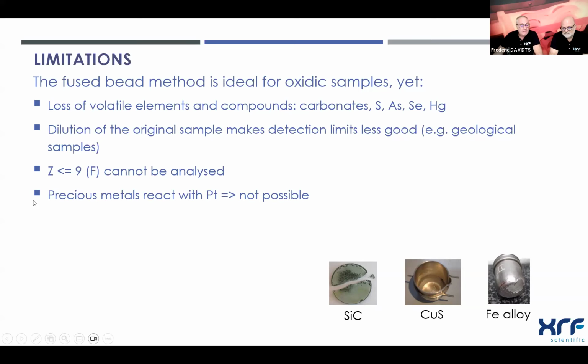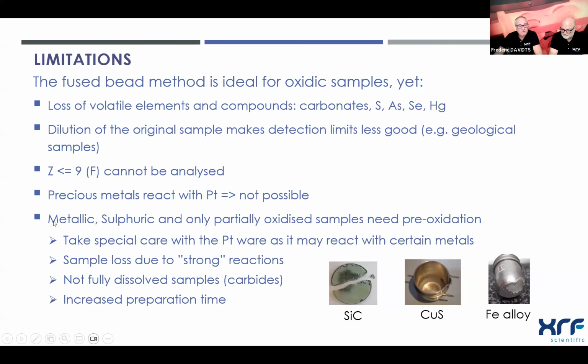Also bear in mind that precious metals like gold, silver may react or will react with platinum. So it's not possible to make fused beads and analyze those elements. And as mentioned before, metallic sulfuric samples or only partially oxidic samples will need some pre-oxidation. So we need to take special care because we may ruin our platinum or we may have very bad quality fused beads, so we have to be very, very careful. But always remember, XRF Scientific can give you indications when you have a special sample and you're not sure how you have to prepare it. Please contact us, we can help you.